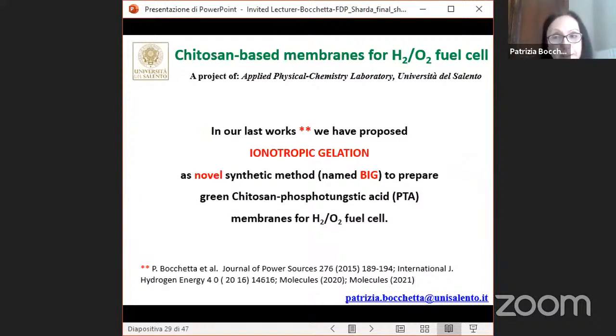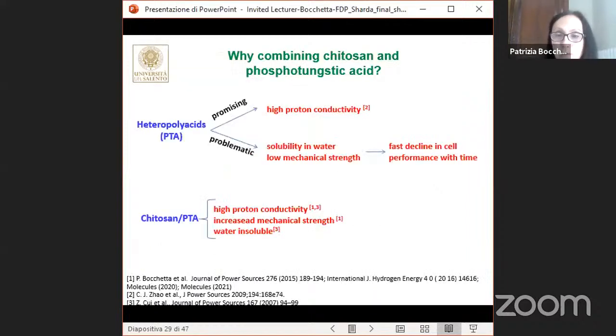So, in our last works, we have proposed this method, ionotropic gelation, as a novel synthetic method, named BIG in the following slides, to prepare green chitosan phosphotungstic acid membranes for hydrogen-oxygen fuel cells. Now I show you some of the more representative experimental results we have obtained. First of all, we have to answer the question: why combine chitosan and phosphotungstic acid? It is known that phosphotungstic acid has a very high proton conductivity, in the order of 10 to the -1 Siemens per centimeter at 25 degrees centigrade, together with non-corrosive, environmentally friendly features.